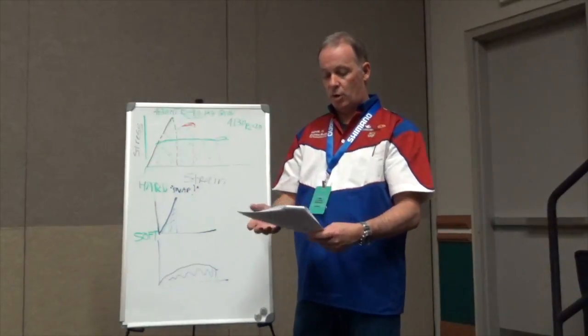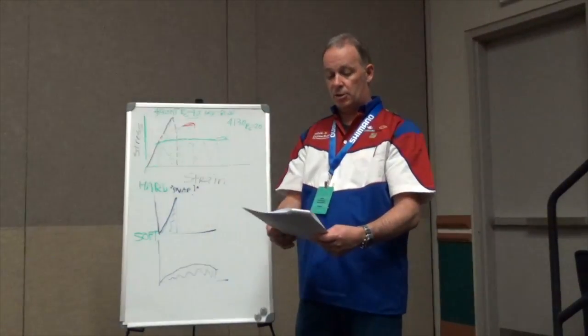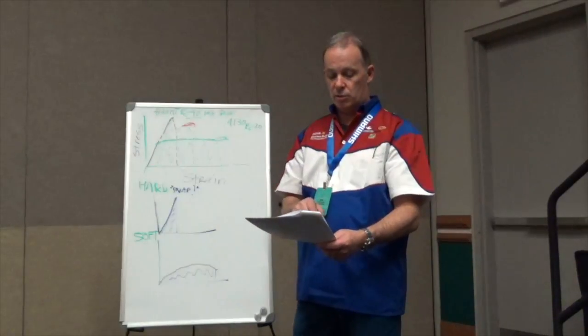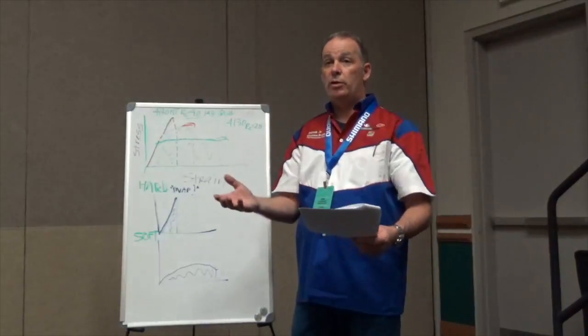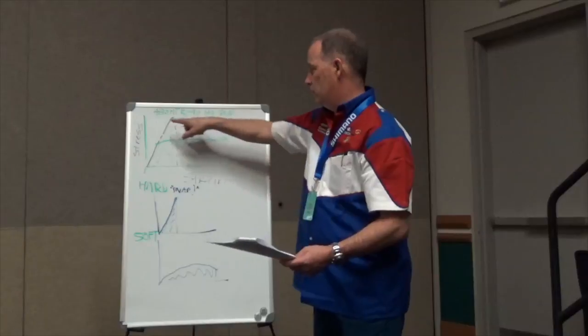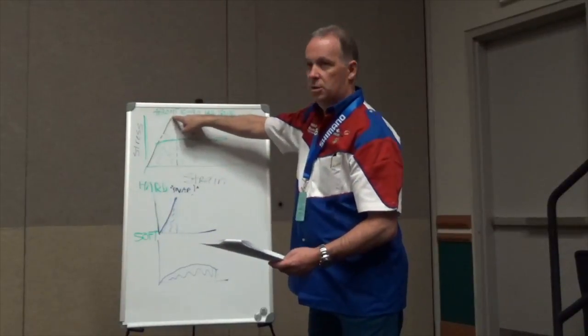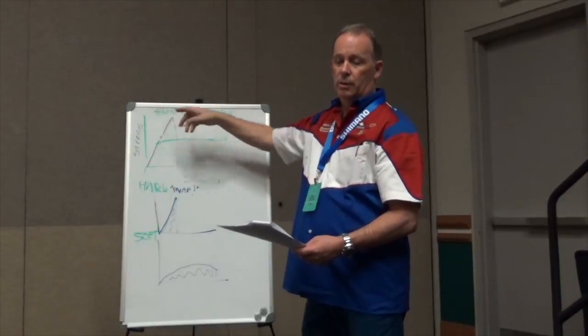Yeah, these were assumptions. If you go halfway down the page, it'll say assumptions of what would happen in heat-affected zones. The weakest spot that should fail is the heat-affected zone because the strength is the lowest. That's what we thought. And the material with the highest published tensile strengths should be strongest. Well, I've kind of given you a preview that the highest is not necessarily the best in failure.